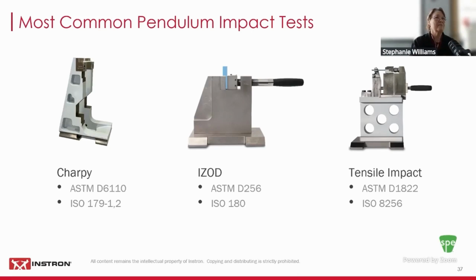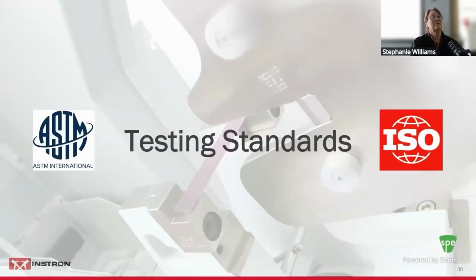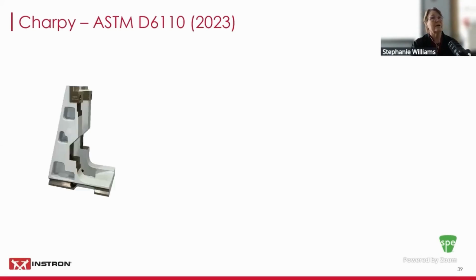These are Charpy, Izod, and tensile impact. These are the most commonly run tests on a pendulum itself. So if we look to the testing standards, start with your Charpy. So the ASTM D6110 was revised in 2023. Some things to keep in mind is the sample itself is placed horizontal to the impact plane with the notch facing away from the point of impact, and we center on the notch.